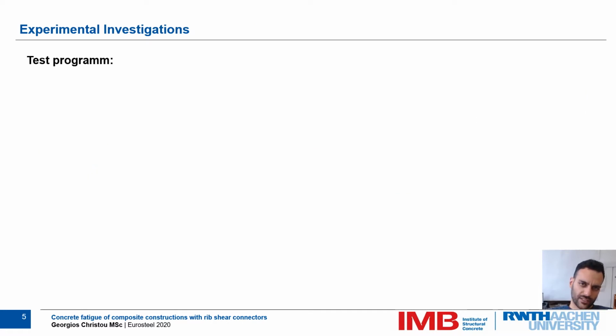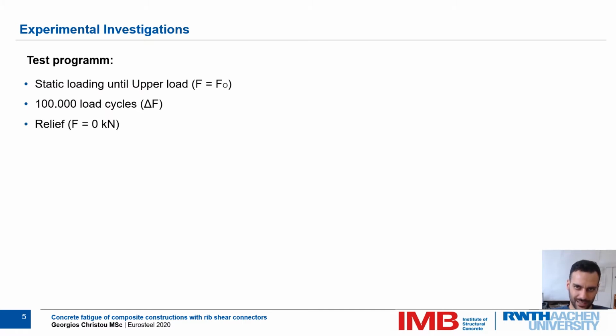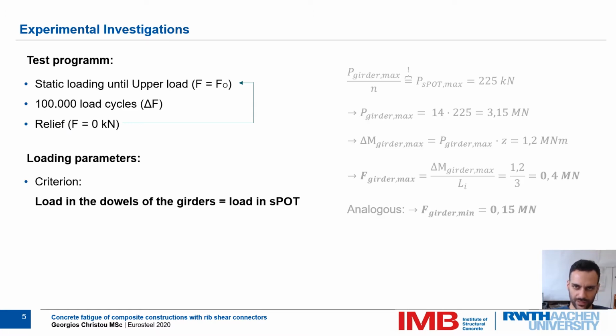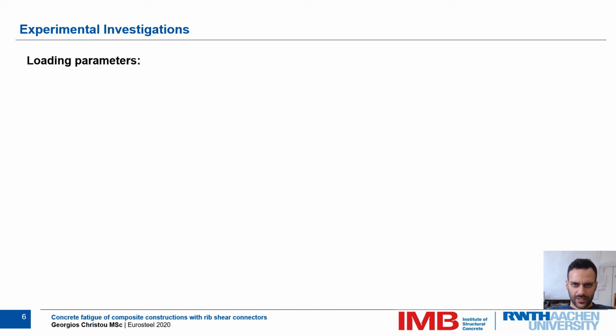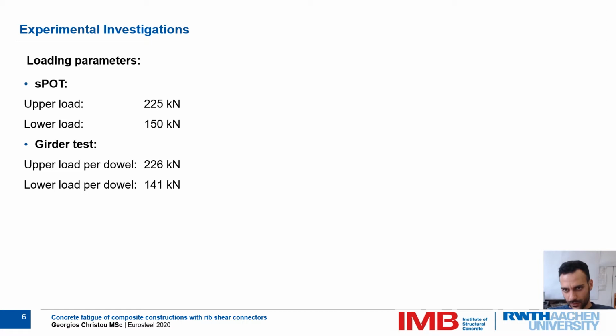The test program for both the single push-out tests and the girder tests consisted of an initial static loading to the upper load, 100,000 load cycles, and a relief of the load, after which we started over. The latter allowed us to capture the evolution of the static stiffness of the specimen over the lifespan. The load parameters were chosen with the criterion that the shear forces per dowel in the girder shall be equal to the ones we chose in the single push-out tests. The upper load per dowel was chosen as 225 kilonewtons and the lower load as 150 kilonewtons for the single push-out test, and approximately 140 kilonewtons for the girders.